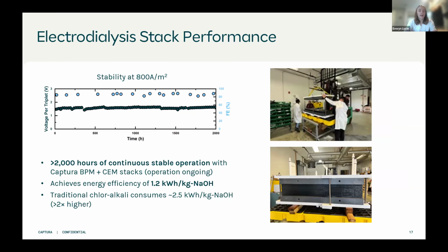And a good comparison here, so if you look at our voltage and our efficiency, we're able to achieve about 1.2 kilowatt hours per kilogram of sodium hydroxide, which is a pretty industry standard way of measuring their energy needs. And if you compare this to the standard way that sodium hydroxide is produced, which is called the chloralkali process, we're less than half the energy needed for this process, and we produce acid at the same time that we're producing the base.